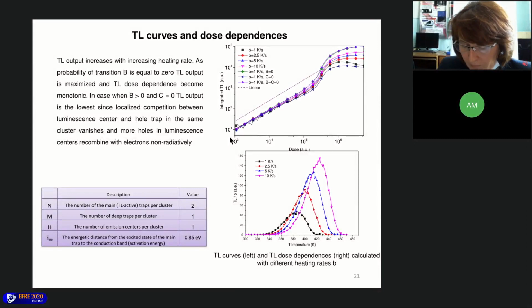Let us describe the case when the activation energy of the cluster is equal to 0.85 electron volts. TL output still increases with increasing heating rate. As the probability of transition B is equal to 0, TL output is maximized and the TL dose dependence becomes monotonic. In the case when B is more than 0 and the probability of transition C is equal to 0, TL output is the lowest, since the localized competition between the luminescence center and the hole trap in the same cluster vanishes and more holes in the luminescence center recombine with electrons non-radiatively. The non-monotony of dependencies is hardly noticeable, but the presence of regions with different non-linearity index remains.